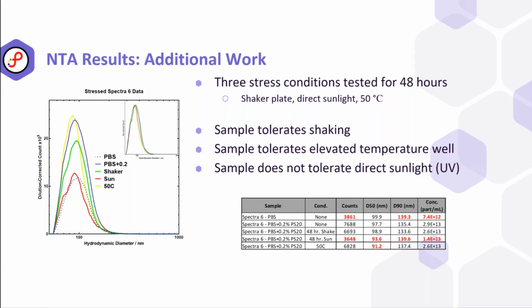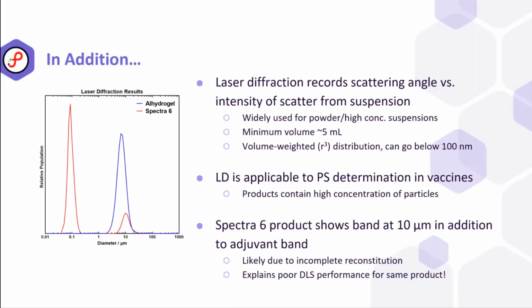Now, moving away from NTA, because laser diffraction was one of the first things I actually worked on outside of the spectroscopic community, let's look at how laser diffraction, a different type of light scattering method, could be deployed here. The first time I saw this working in the vaccine field was about 12 years ago, on a client visit where they were measuring an alhydrogel, or aluminum hydroxide, adjuvant that they had included in one of their vaccines. They were using this as a routine analysis tool when they would receive new lots of material and after manufacture. So that blue curve that you see there is actually an alhydrogel sample that Julie and I were able to obtain and measure.